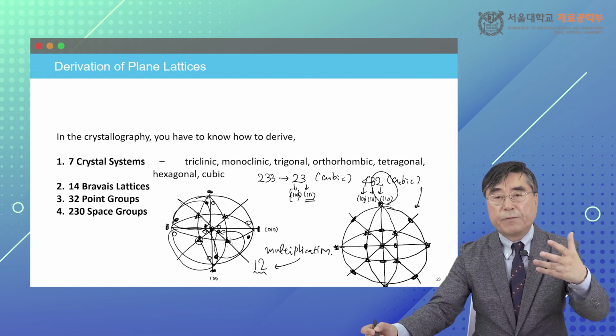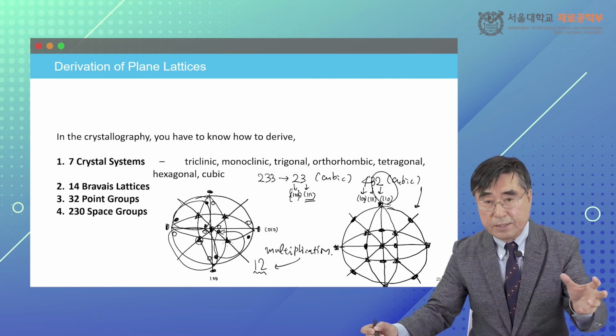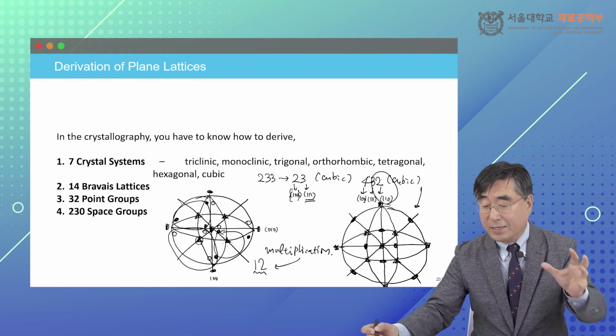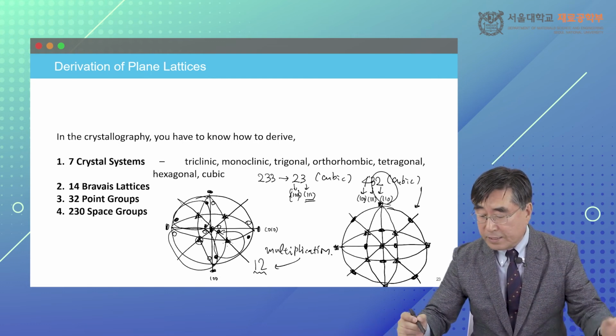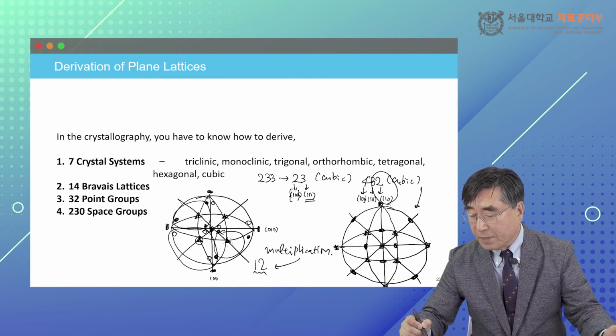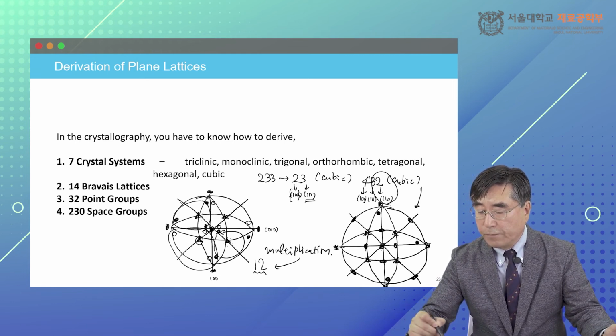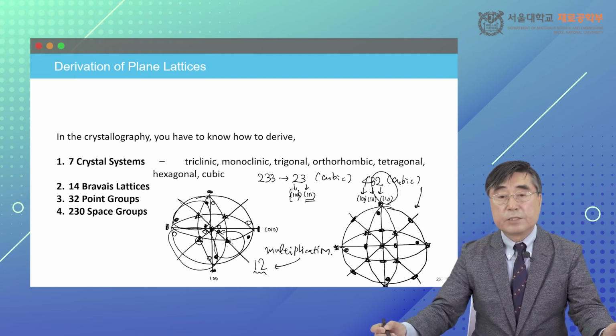Now, you have to find out how many poles are generated in this symmetry. What is the multiplication factor? Okay, it's not easy, but let's just do it one by one. This is quite complicated. For instance, if I have any pole in here, then this fourfold rotation generates 4 poles in here, 4 in here, and 4 in here. This is just the fourfold axis operation.